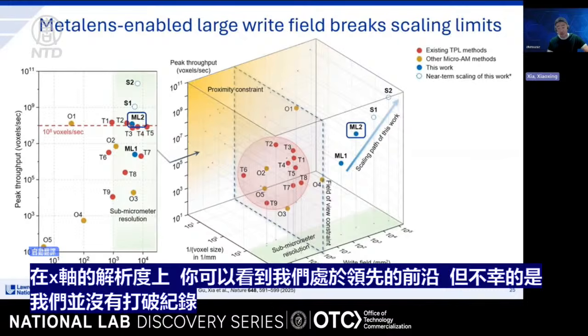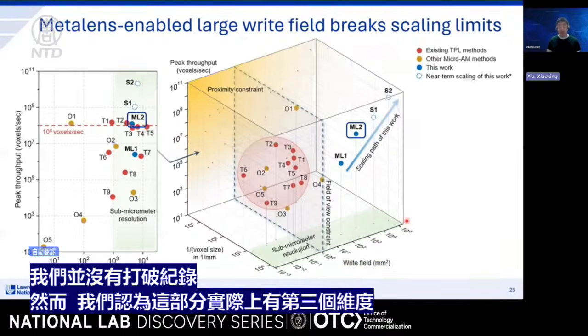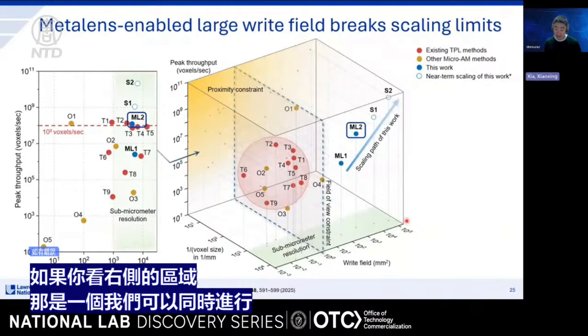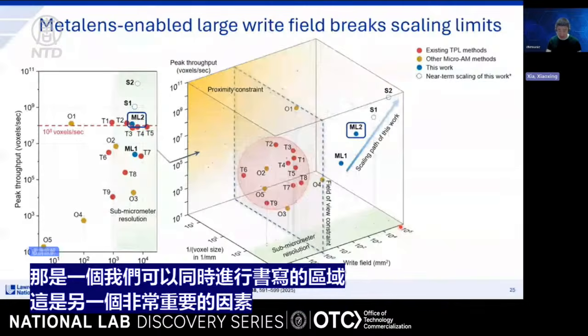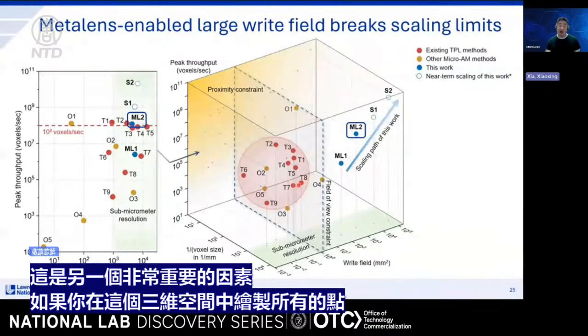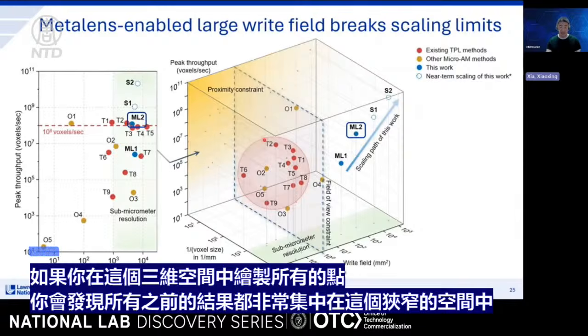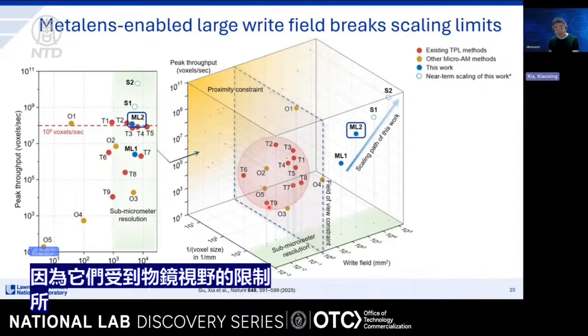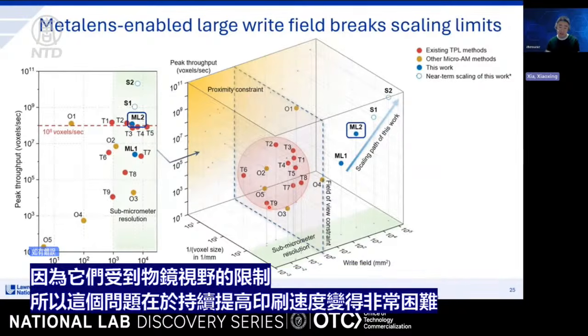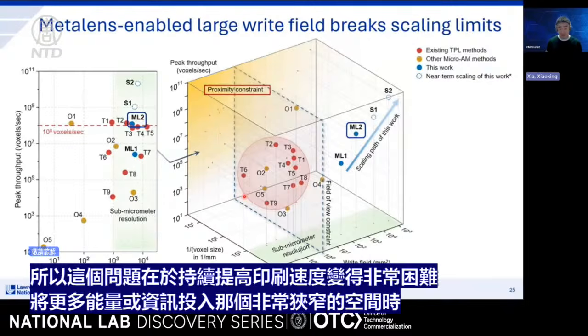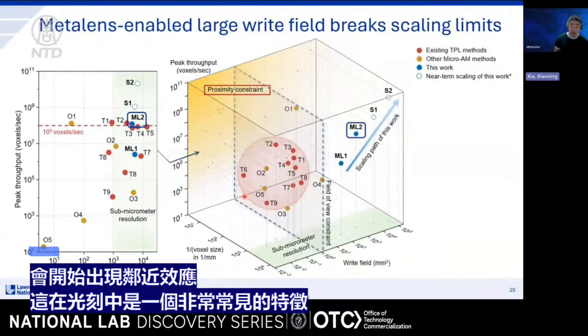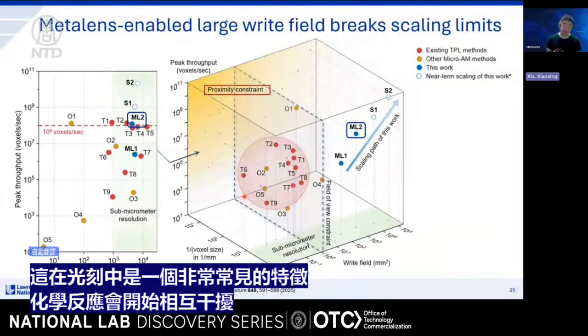If you look here, the z-axis is the area of writing that we can do simultaneously. It's another very important factor. If you plot all the points in this 3D space, you can see that all the previous results are very clustered in this very tight space because they're limited by the field of view of the objective. The problem with that is it's really hard to continue to improve the printing speed. If you put more energy or more information into that very tight space, you start to have proximity effect. That is a very common feature in lithography, where the chemical reactions start to interfere with each other.